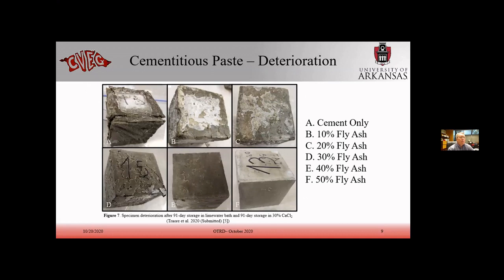So just kind of a visual representation of the deterioration. Once again, these are stored in lime water for 91 days, taken out, then put into a 30% calcium chloride solution for another 91 days. And you can see visually the damage that occurred and how well the fly ash did at mitigating that damage. You can start up here with cement only, and then increasing by 10% down to where we get to 50% fly ash.